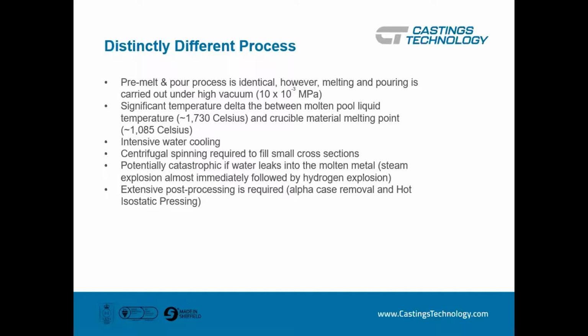And what we need to avoid at all costs is any water getting the wrong side of the copper. Because if that happens, you're elevating that water, which is probably at 4 or 5 degrees Celsius, to 1735 instantaneously, which creates some expansion, shall we say. And then the titanium goes, I'm having all of that oxygen, I'm going to attach myself to it, leaving the hydrogen atoms, which then ignite because of the temperature. So you get a bang, bang, steam, hydrogen explosion. So managing the melting of titanium is expensive and potentially quite dangerous. There's obviously a lot of process controls in place to avoid that, but it is a concern and something we have to manage.